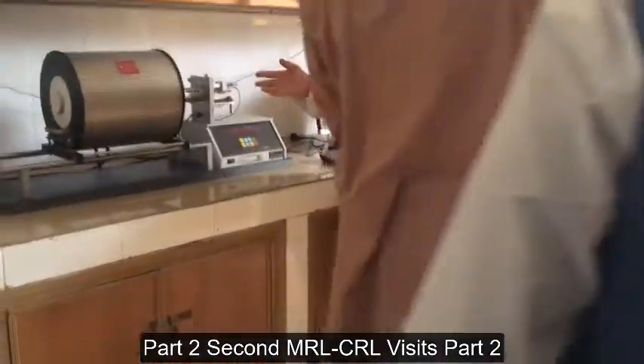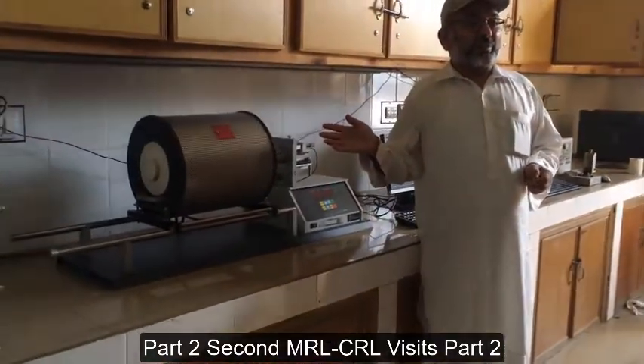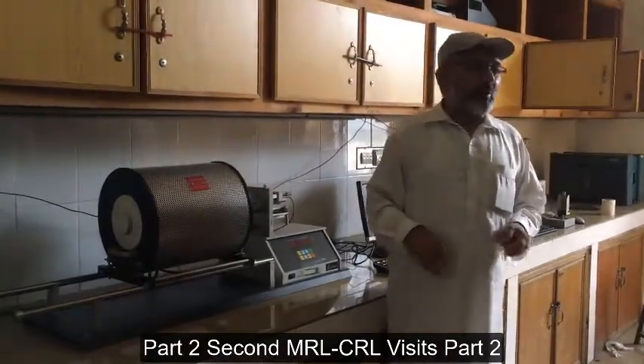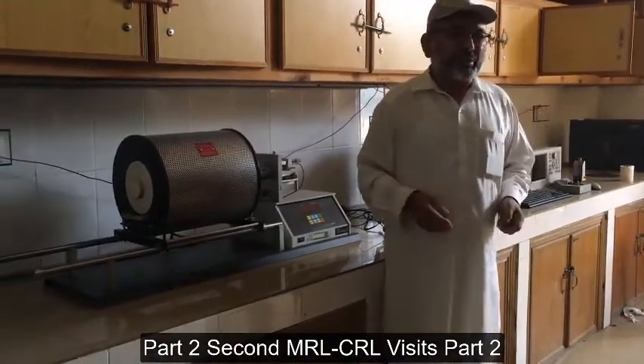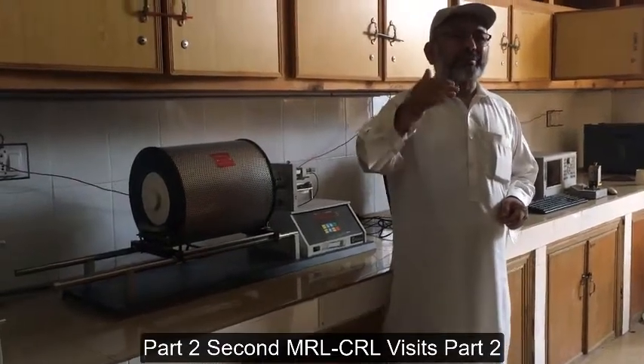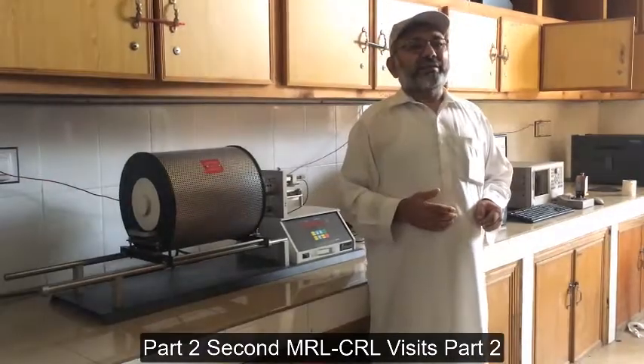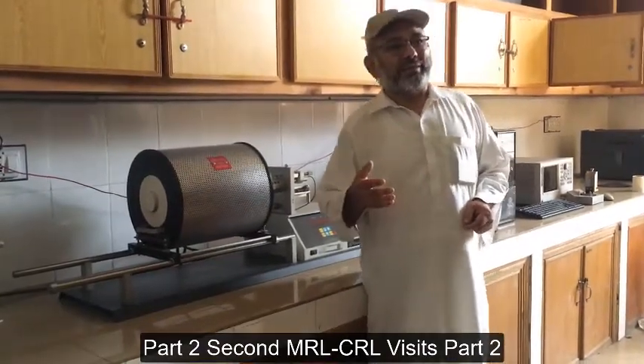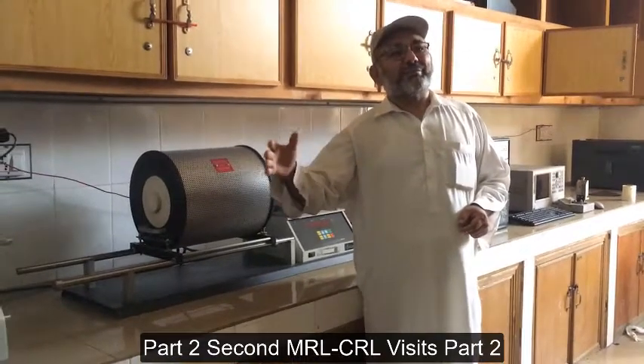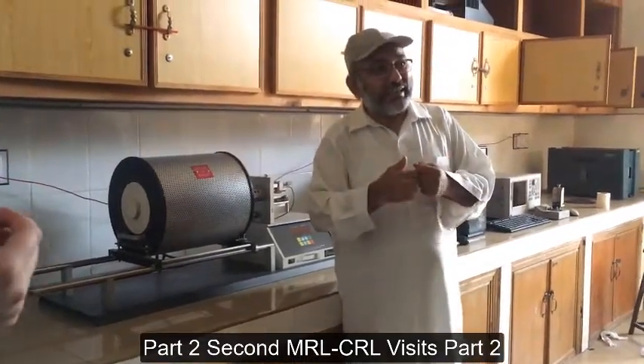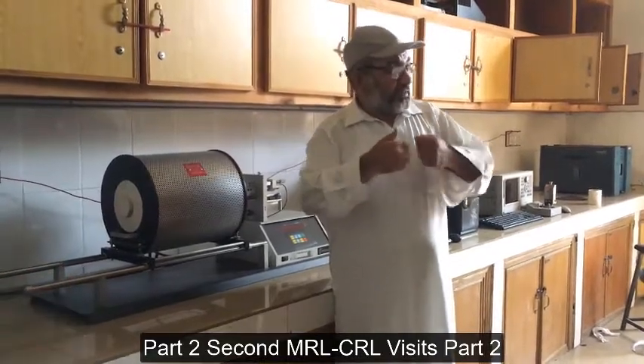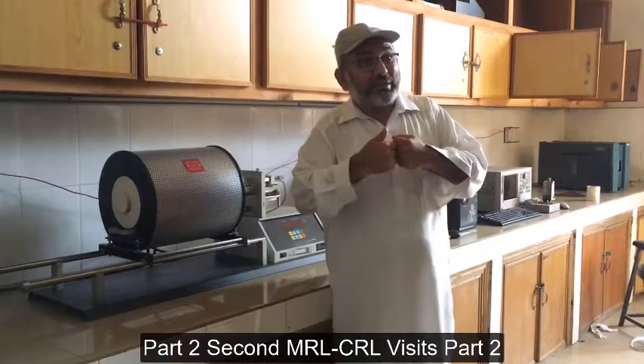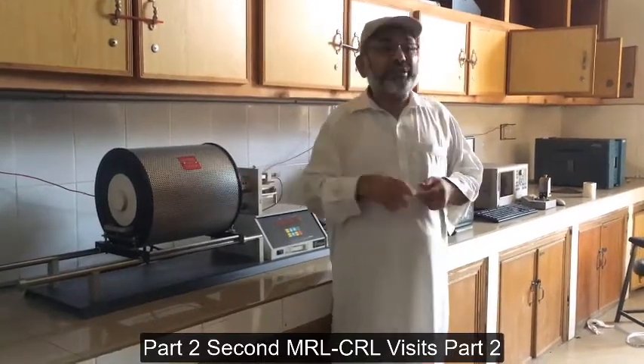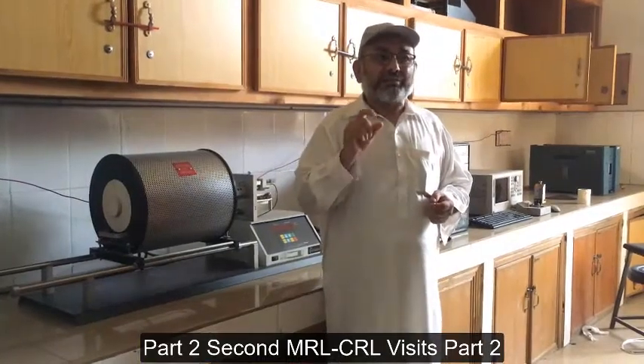Here, this is called a dilatometer, and you measure the thermal expansion coefficient of the material, which is very important, particularly for materials which undergo variation of temperature. Usually in porcelain, when you increase the temperature, the quartz grains are transformed into cristobalite. Their thermal expansion coefficient is different from the surrounding glass, and it starts cracking because it wants to expand, and the glass doesn't allow it, and cracking occurs. So with this machine you can measure the thermal expansion coefficient of different materials.